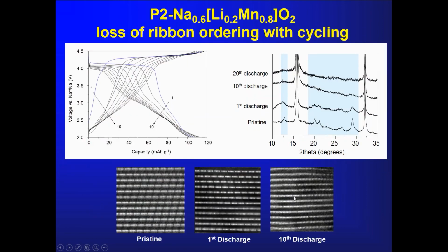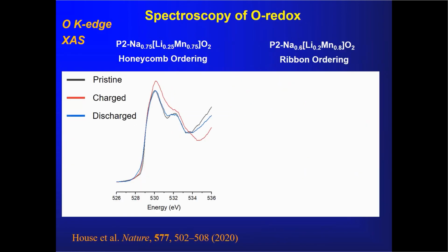I won't dwell on this slide. It just shows you that, as I say, this material will disorder on multiple cycling. I think the interesting point on this slide that I wanted to bring out, these are some X-ray absorption spectra as opposed to RIXS. And on the left, you see the pristine spectrum in black, the charged spectrum in red, and the discharged in blue. And this is for our honeycomb structure again. And so these extra absorptions here represent, now we're mapping out the whole states above the Fermi level. This represents the molecular oxygen formation.